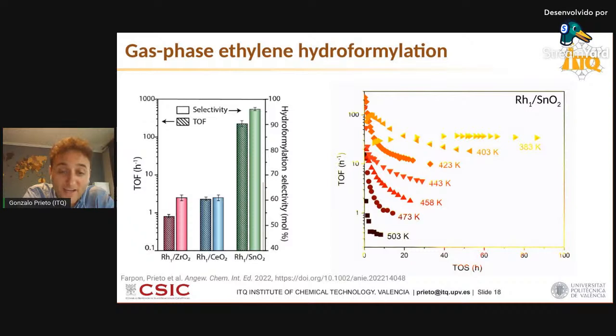This is what I'm showing on the right-hand side as a function of the time on stream, so the reaction time. You can see that at quite mild reaction temperatures, around 110 degrees C, this catalyst can show a remarkable turnover frequency, essentially full selectivity, and quite good stability. But then as we keep on increasing the operation temperature, and especially beyond 150 degrees C, the catalyst starts to lose activity at a very fast pace, and a pace that increases monotonically with increasing operation temperature, to the point that if we go beyond 200 degrees C, then the catalyst is only active for a few minutes.